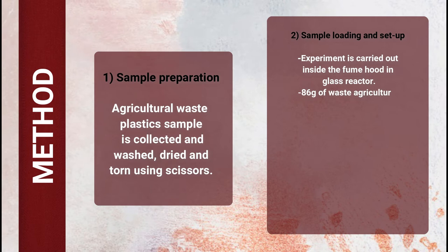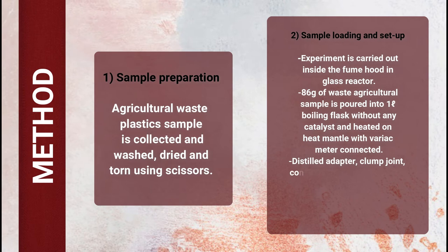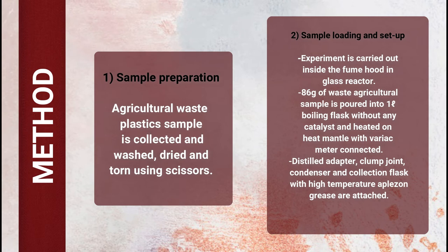A weighed sample of waste agricultural plastic will be poured into a one-liter boiling flask without any catalyst and heated on a heating mantle with a variac meter connected. The distillation adapter, clamp joints, condenser, and collection flask with high-temperature grease will be attached.